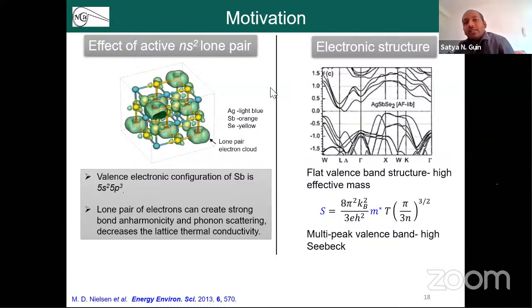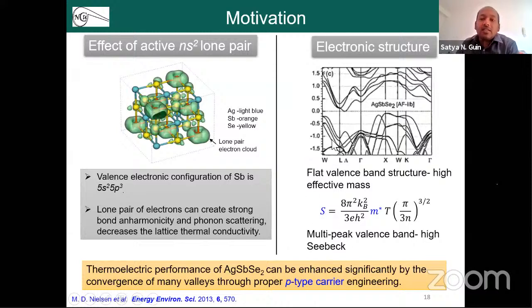Another important point is it has a very favorable electronic structure. It has multiple flat bands in the system, which results in a high carrier effective mass, which is important to get a high Seebeck coefficient, as you can see from the Mott equation. Now we know that it has a good Seebeck coefficient and low thermal conductivity. And another important parameter, as I told you, is that you need to have good electrical conductivity. So for that, we try to do carrier engineering of this system by doping with a P-type dopant. Okay, so this is the idea to start this work.